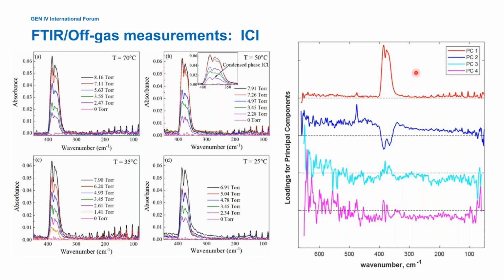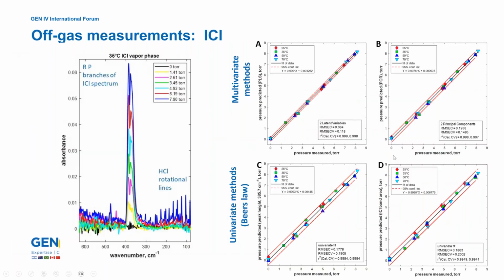And this plot here shows the principal component analysis of this data that I'm showing over here on the left-hand side. The principal component analysis of that shows that essentially two PCs are needed to define all of the character in both the variable temperature and variable pressure that we see in the ICl spectra. PC 3 and 4 are shown here only to show that these show essentially noise, and they can be excluded. Any PCs higher than PC 2 could be excluded from forming a regression model. And we use these PCs to form regression models in multivariate method.